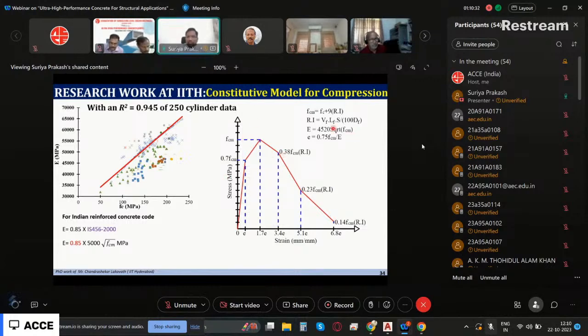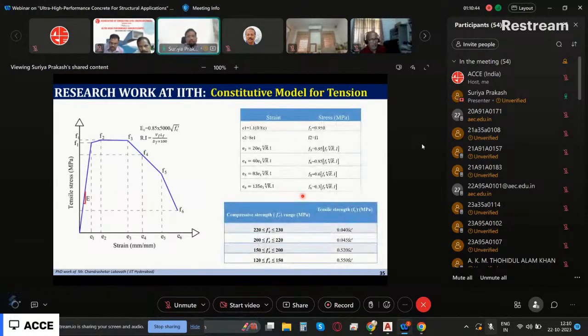And this RI is your fiber reinforcing index parameter. If you give the length of the fiber and the volume fraction of the fiber, then I can get the stress strain curve equation. Like that, we came up with a stress strain curve for tension also, because in regular reinforced concrete design, anything that is below the neutral axis in flexure, we say that concrete is not going to contribute in tension. But this material is going to give very high tensile strength, so we cannot ignore that. That is the biggest advantage with this material.